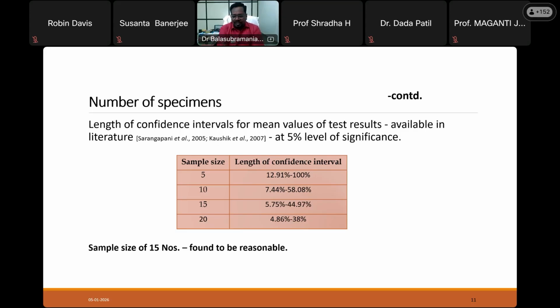the values, the length of confidence intervals that are reported pertaining to different studies where they have reported the average value and COV in some instances, or in some instances they may not have reported. We computed. Okay, for a sample size of 5, we obtained the length of confidence interval between like 12.91 to 100, and then for sample size of 10, it was between 7.44 to 58.08, which is drastically reduced, right?